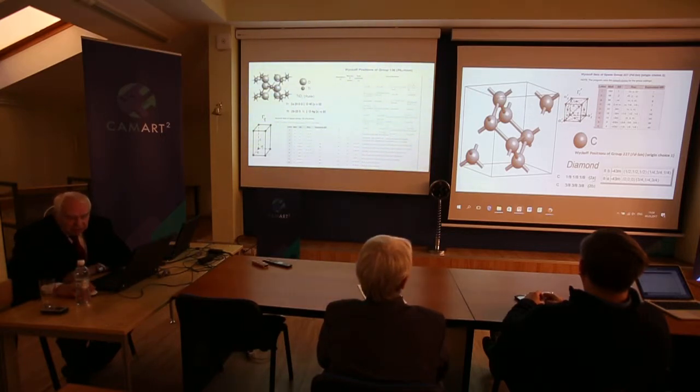Therefore, 2A and 2B. I already told yesterday that when I write 2A and 2B, the crystallographer says, no, you need to write 8. But I say, nobody who calculates phonons or electron states will do it with 4. They will consider a primitive unit cell with 2 carbon atoms. Nothing more. No 4. No 8. Two equivalent descriptions, either A or B.